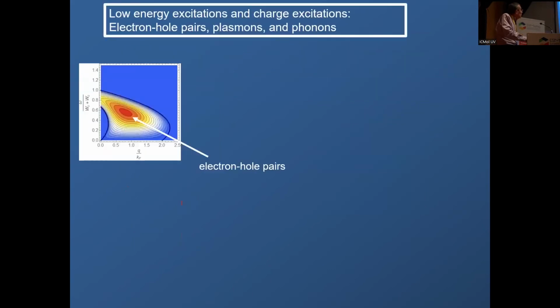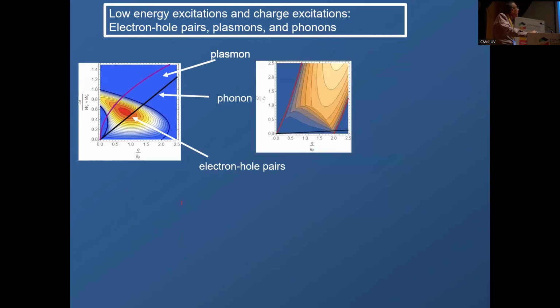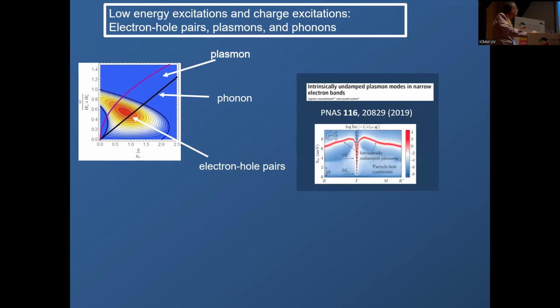The generalization to twisted bilayer graphene is more complex, because basically the pairing associated with the Kohn-Luttinger mechanism is a pairing by electrons themselves, by electron-hole pairs. But these electron-hole pairs in graphene are at very low energy because the band is very narrow, and the plasmons associated with these partially filled bands are also at low energies. And not only that, but the phonons themselves overlap with these two spectra, unlike what happens in a conventional electron gas, which is shown here. There, you have a wide band, electron-hole pairs have high energy, phonons have low energy, and they basically live in different worlds. These are our previous calculations, and these are our calculations.